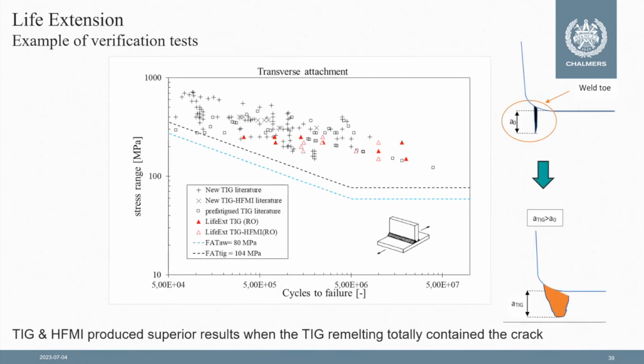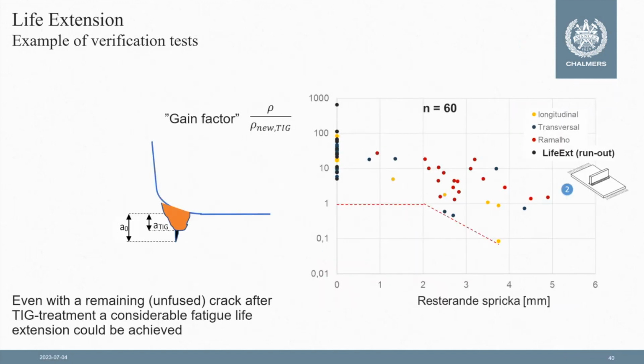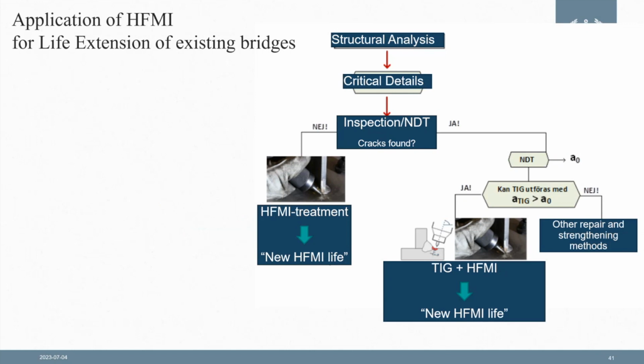Similar things can also be said about TIG dressing. When TIG was applied on a cracked detail, under the condition that the TIG dressing is deep enough to cover the full crack, it produced results very similar to a new TIG dressed detail, which is, of course, also very good. Also, in the case of TIG dressing in which the pre-existing crack is deeper than the area that was remelted, there was an enhancement in fatigue strength. Even with a remaining crack of 2 millimeters, we could observe an extension of the fatigue life corresponding to that of a new TIG dressed detail. So that gives some degree of redundancy, let's say.